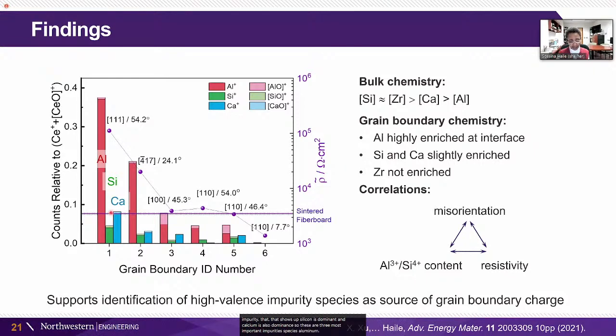Aluminum and silicon lead to high space charge potential from our calculations because they have high charge and they are not substitutional elements. They go right into the grain boundary. Calcium is a substitutional species and has lower charge. And so it tends to screen the space charge. And we can see now that if we compare the impurity concentrations to the conductivities, this is now resistivity, that the higher the impurity concentration, the higher the overall impedance across that interface.